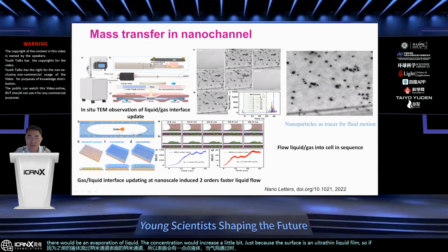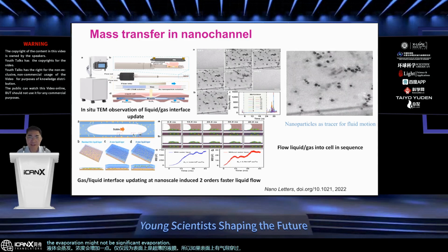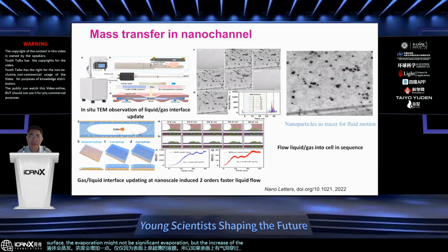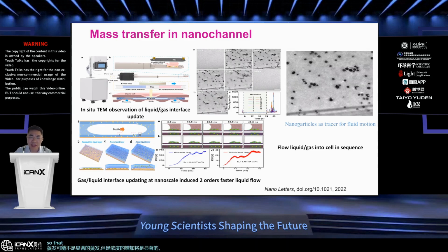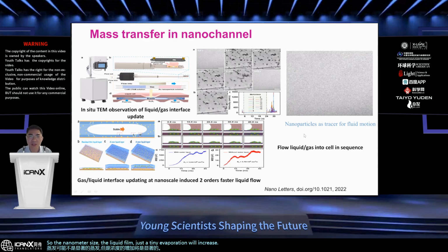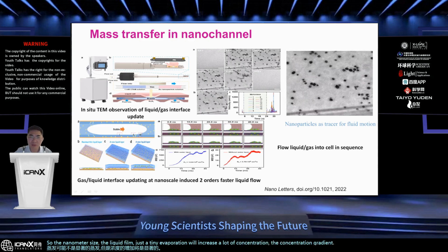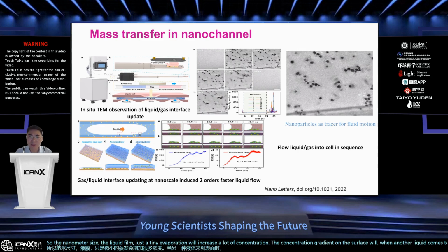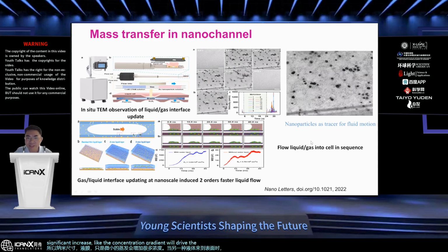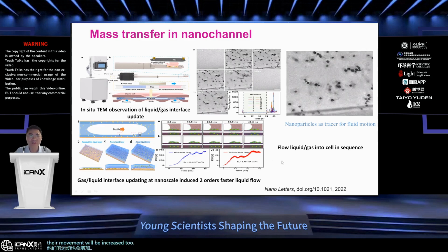The concentration will increase a little, because on the surface it is an ultra thin liquid film. So if a bubble goes through, the evaporation might not be significant, but the increase of concentration would be a lot. For a nanometer size liquid film, just a tiny evaporation will increase the concentration a lot. When another liquid comes to the surface, the concentration gradient will drive the nanoparticles inside the liquid to move. Their movement will be increased by 2 orders.